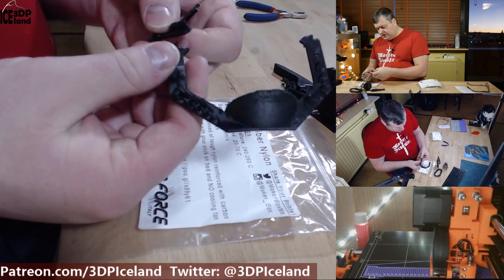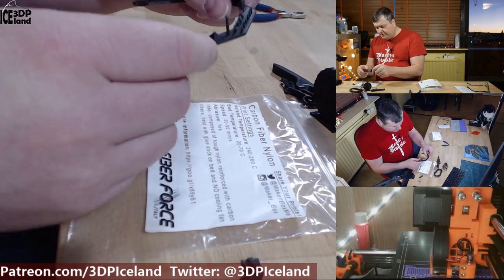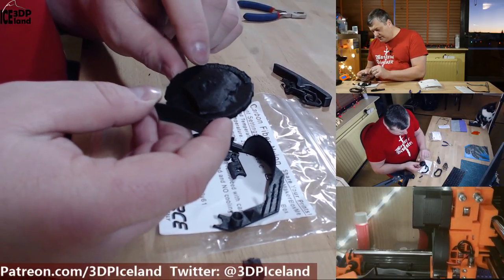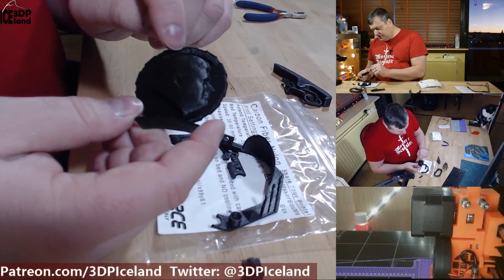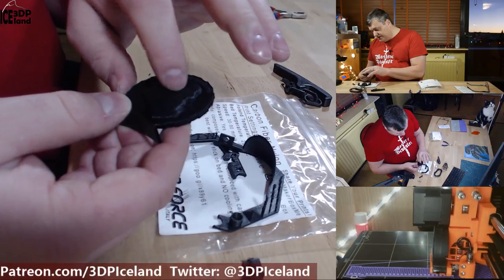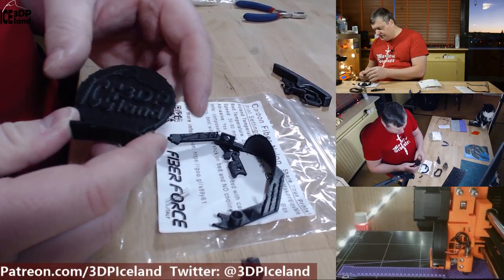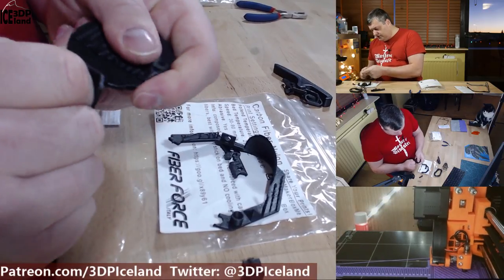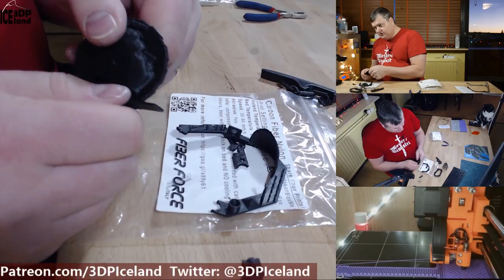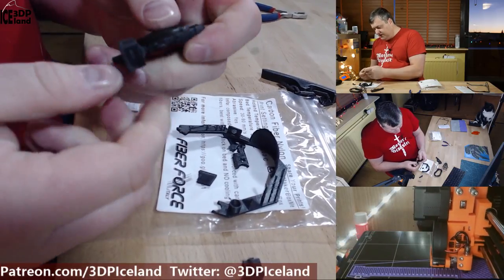I cut the test piece to try out the strength — it's really tough material, a nylon reinforced with carbon fiber, so it's a very strong filament. I then printed out my MakerCoin, and the detail in the letters is a bit smudged together, but it's difficult to see because it's a black filament. The surface finish is great and you can't see any layer lines — all the layers are fused together with very strong layer adhesion. I can't even break off the bottom part of the print with my hands; I have to use some tools.